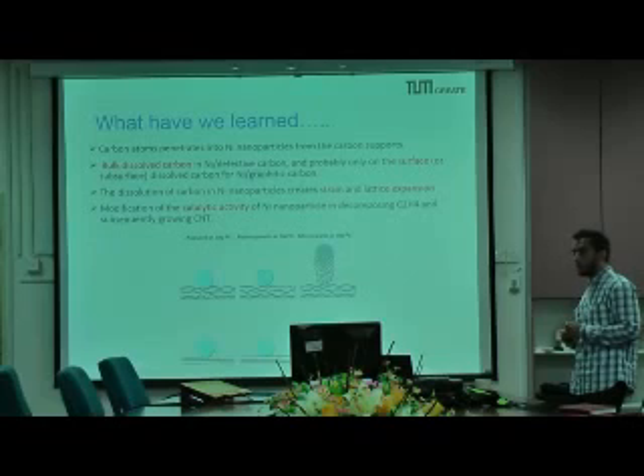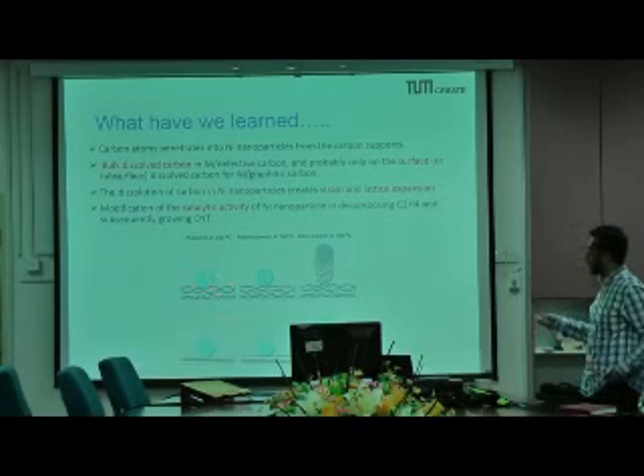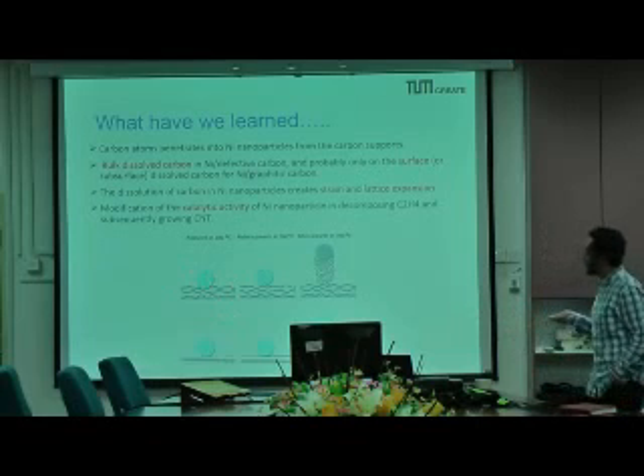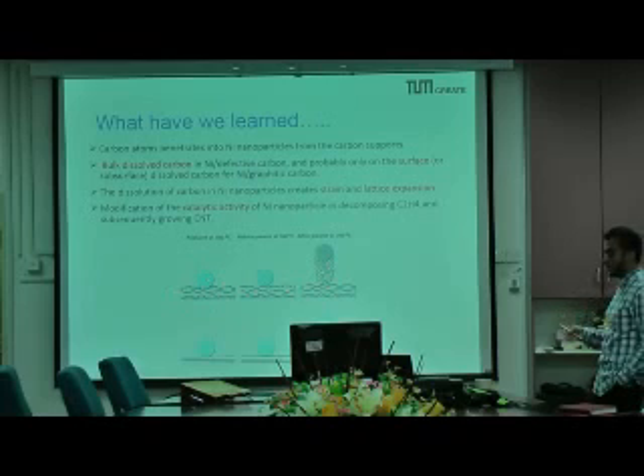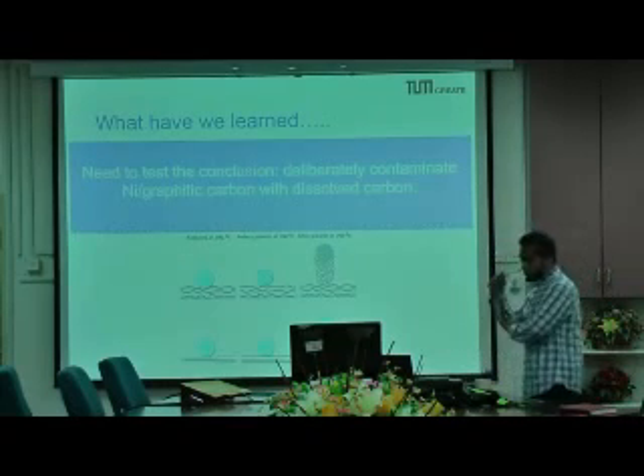So just to come up with a model to simplify the understanding, we put a nickel nanoparticle, or actually the nickel family, they should be the same, or iron. You start to see carbon going in from the defective surface into the catalyst, and this changes the behavior of the material for reactions. But we need to test this summary.